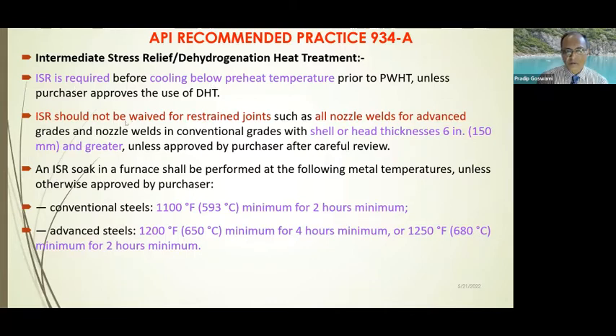And for ISR, the requirement is that it shall not be waived for joints such as nozzles, etc. So what it implies is that ISR is something like a long-time soak. For conventional steel, this ISR is at 593 degrees centigrade or 1100 degrees Fahrenheit. And for the advanced steel, it is 650 degrees centigrade for a minimum of 4 hours, or 680 for a period of 2 hours. And this has to be performed immediately after welding, before the subsequent post-weld heat treatment is done for the shells or for the components which are fabricated.